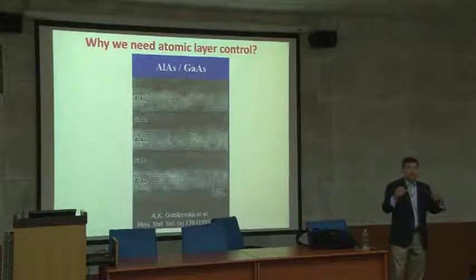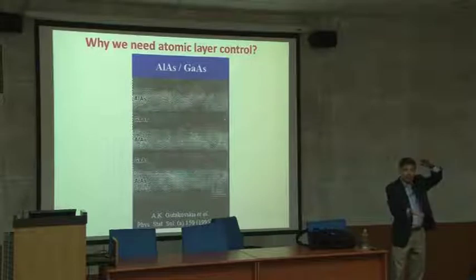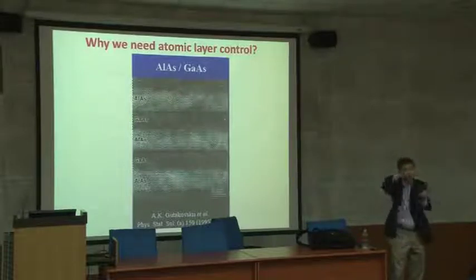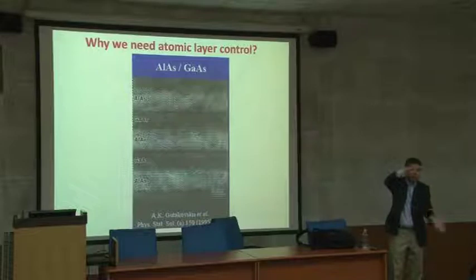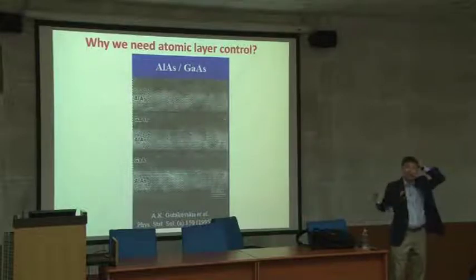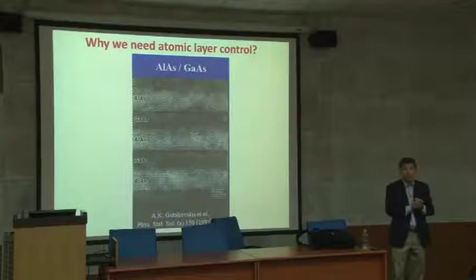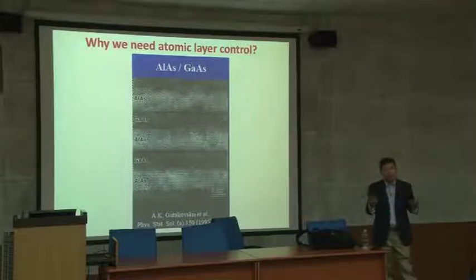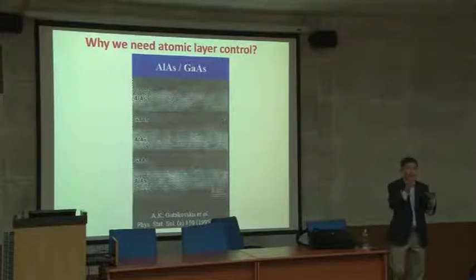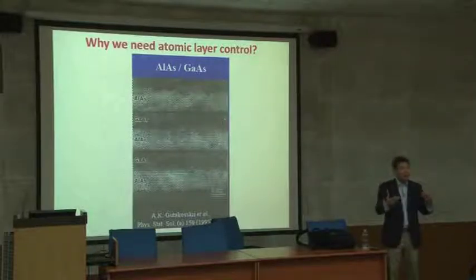When your dimension gets smaller and smaller, this patch can be phased to the polar surface observed in the bottom electrode and become ferroelectric. That was published in 2015 in Science. That's what we call ferroelectricity at room temperature at reduced dimension, which I'm going to talk about later. You brought a very important question, and those are the two ways we can do it. You can not only enhance the ferroelectricity of a certain material, you can also make a non-ferroelectric material ferroelectric.